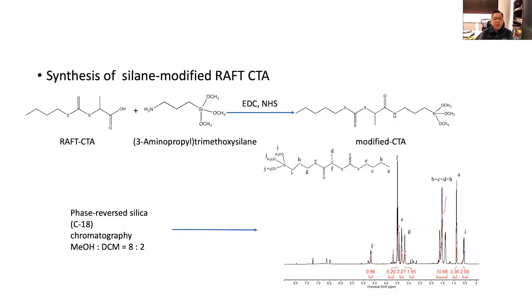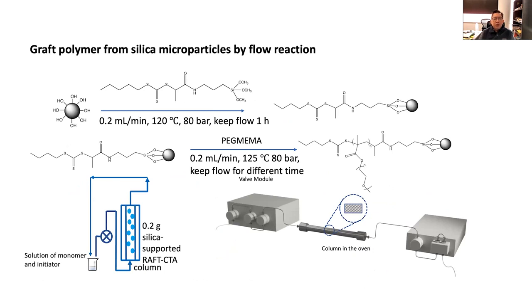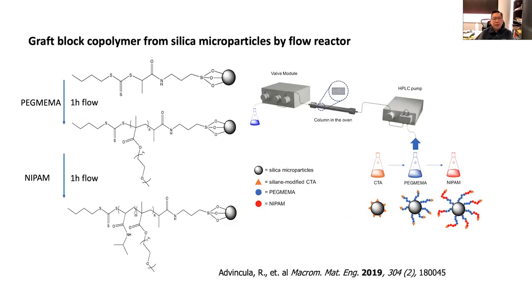So taking this cue, we synthesize a chain transfer agent that can be attached on the surface with silane chemistry, as shown here. And then we introduce this on a particle. This case was in the form of a silica gel and some metal oxide particles. Here, you can see the attachment on a surface, followed by reaction based on the chain transfer agent, and then catching the product. So the whole setup was done in a column where the particles are packed in a column. And I'll show you later how those particles look like.